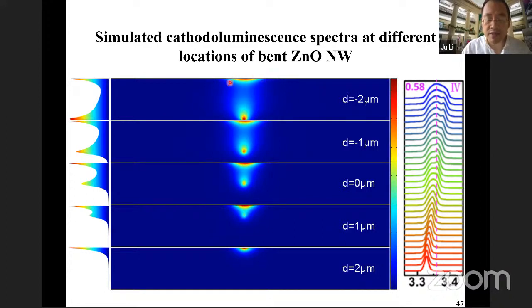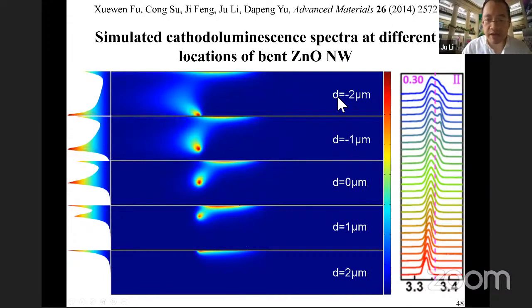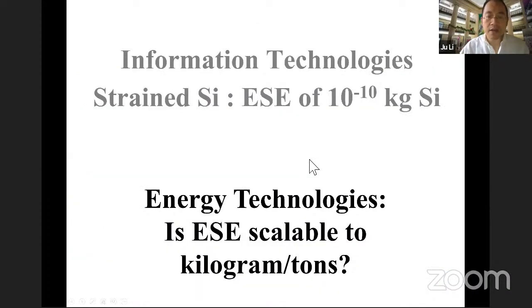And at steady state, this is the distribution of the electronic excitation in this nanowire, and so you would have this broadening of the light color. And in fact, you can also apply a longitudinal strain as well, and you can basically tune the color spectrum. Now, those two examples demonstrate you can use strain to regulate the flow of photons or electrons. So that's enough for IT because you really don't need a lot of material. In fact, in your computer chip, in your laptop, you probably only have this much strained silicon, and that's enough.